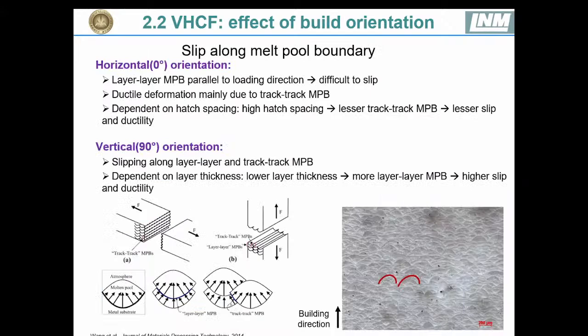And then one question may arise: what is the reason for the build orientation on the very high cycle fatigue? Why the horizontal build specimen has a higher fatigue and also tensile property than those built with 90-degree orientations here? One reason can be due to the molten pool shape. We know that there are two molten shapes. One is layer by layer, which is that in different layers, and there will be several layers of this molten pool boundary. And when the molten pool is parallel, they are track by track molten pool.